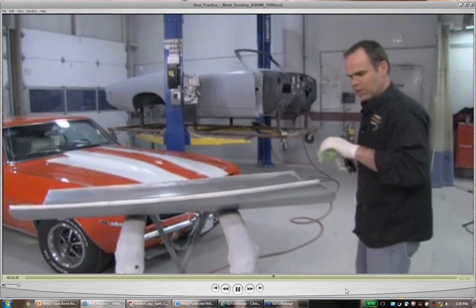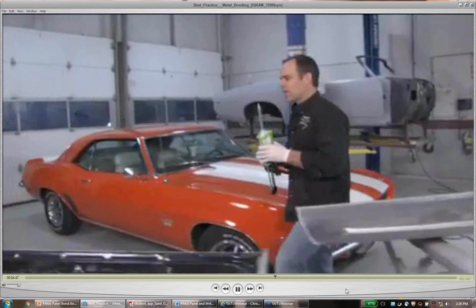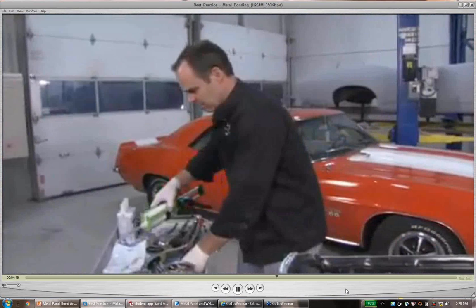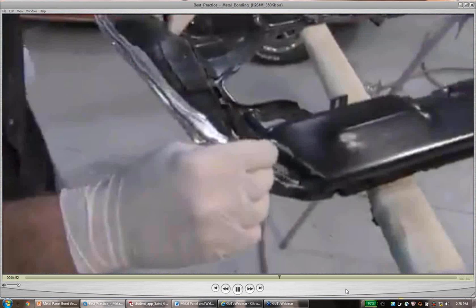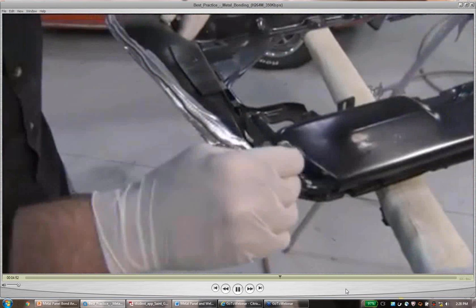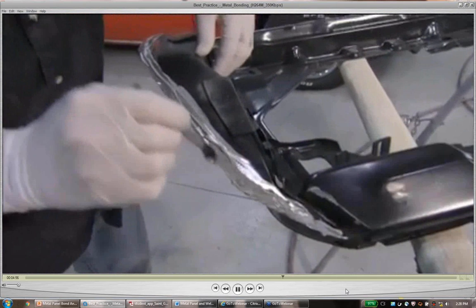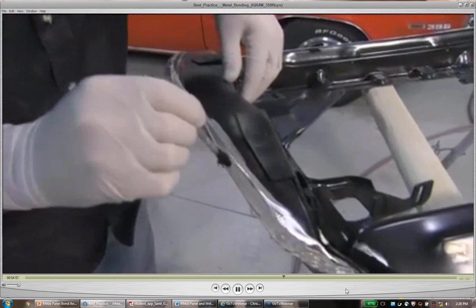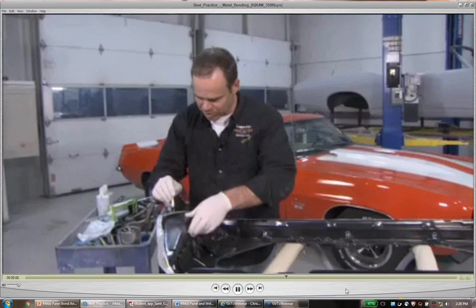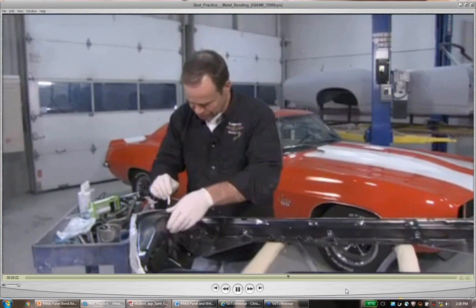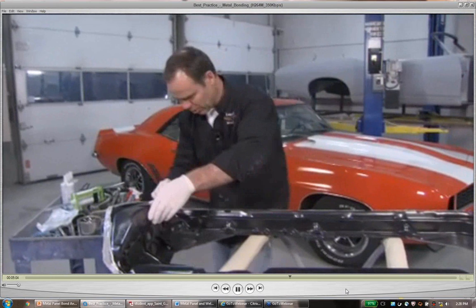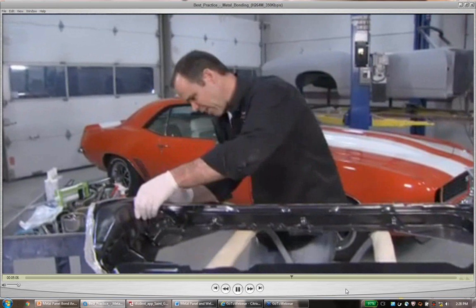Then your next step is you're going to take an acid brush. Just start wiping it, making sure we got good coverage right to the edge. The nice part of either one of these systems is you have some time. This is a 45-minute system. You also have a 75-minute system if you're doing a bigger panel.